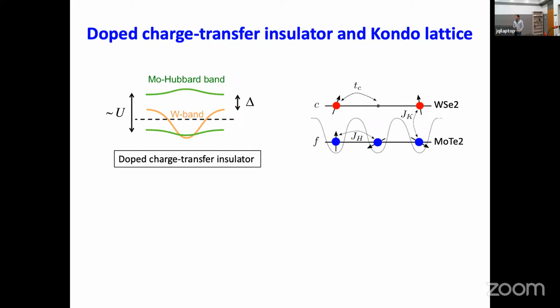Okay, and then the idea now is to dope additional carriers in the tungsten band, so to look at a doped charge transfer insulator. From band structure calculation and from our experiment, the tungsten band is much less flat compared to the Moiré band. So in that respect, it's like an itinerant carrier in the tungsten layer. So once you do this, if the Mott gap of the Moiré layer survives with the doping, then you have a triangular lattice of local moments, and then itinerant carriers on only the monolayer of tungsten selenide.